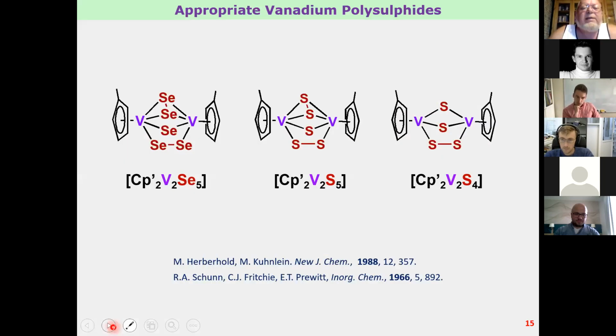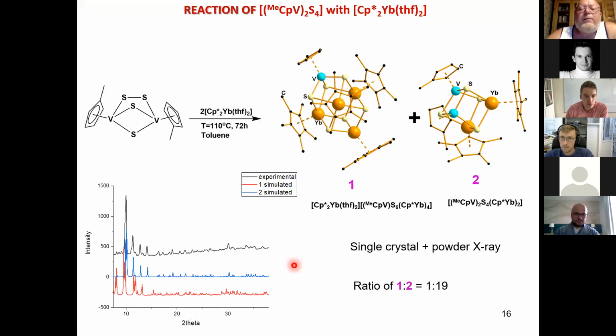And of course, in this case, it's also interesting to go further for new metals, more interesting metals from the magnetic point of view. Shortly, I introduce our last work concerned with vanadium complexes. These complexes, which are shown here, were also involved in redox reactions with some samarium and ytterbium complexes. Here you can see an ytterbium example. In this case, we always have a mixture of products, but using powder diffraction in combination with single crystal diffraction, we can make quantitative analysis, and we know that the major product in this case is this compound 2.